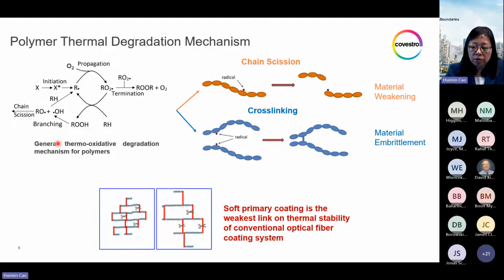Thermal oxidation is a free radical chain reaction process where oxygen not only plays the role of propagating the radicals, but also plays the role of auto-acceleration by chain branching, through a hydroperoxide that decomposes to two radicals. One of the radicals is the oxy radical, which is very unstable and readily goes into chain scission. The consequence of the chain scission is breaking down the cross-linking network of the material, making the material weaker.